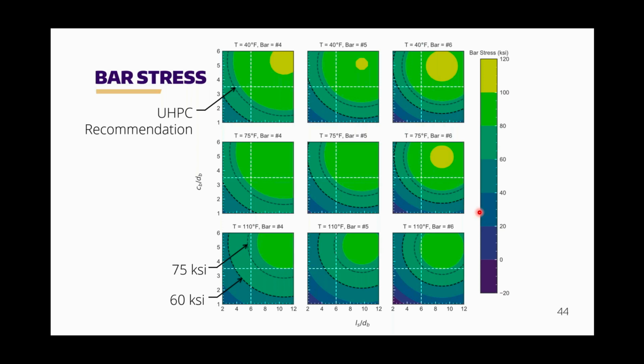So it's all here. We have our 3 different temperatures. 40 degrees Fahrenheit is the top row of plots, 75 degrees Fahrenheit is the center row of plots, 110 degrees Fahrenheit is the bottom row. Bar size, we go from number 4 bars to number 5 bars to number 6 bars on the right. And then within each of these individual plots, we have the normalized splice length on the x-axis and the normalized cover on the y-axis. So we have all 4 of the variables that we investigated, and shown in each of the panes is a contour plot of the bar stress at failure.